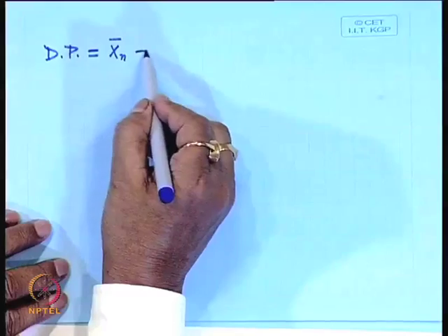Here in a polymer mass, the situation is different. There is a distribution of different sized molecules, and you will get an average. That is why you have to express this molecular mass or molecular weight as an average, might be number average based on number count, or weight average based on weight count. All right, we will discuss later in detail. So, that number average molecular weight